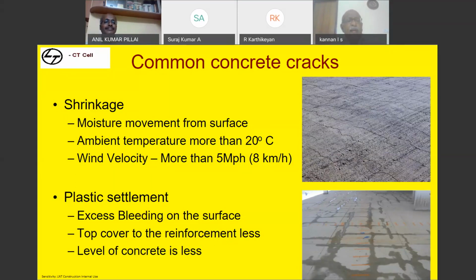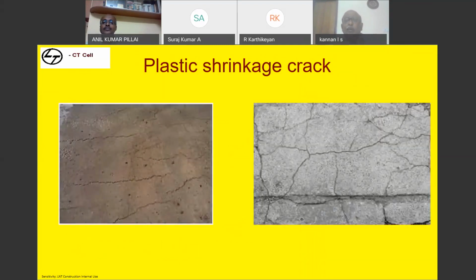Then plastic settlement. Excess bleeding on the surface. Top cover to the reinforcement is less. Level of the concrete is less. Plastic settlement is nothing but, after placement of concrete, you can see some layer lines. That means whatever the reinforcement pattern is, you will be able to see on the top surface. Don't panic with that. This is normally visible within 10 minutes to 3 hours of placement of concrete. I'll discuss in detail how to avoid this. These are some of the photographs of plastic shrinkage cracks.